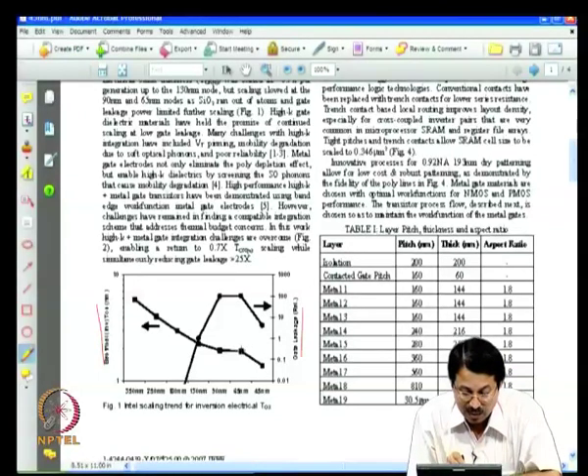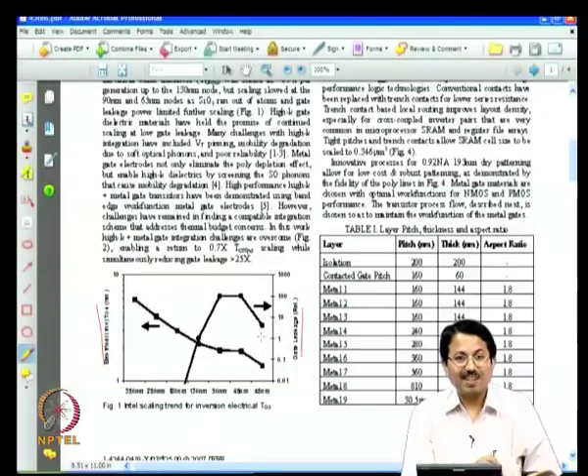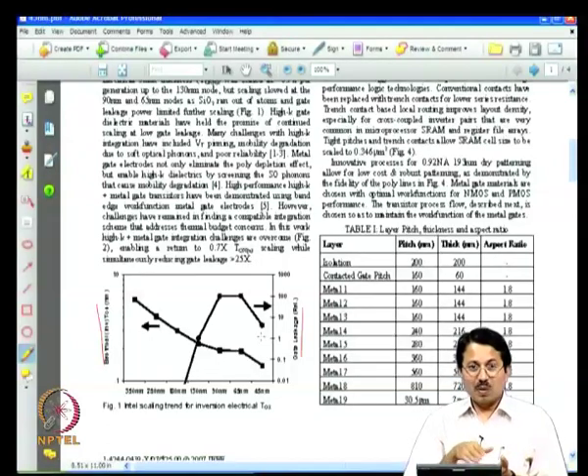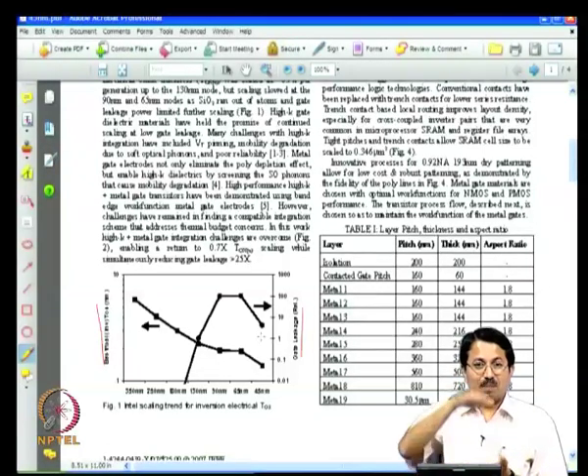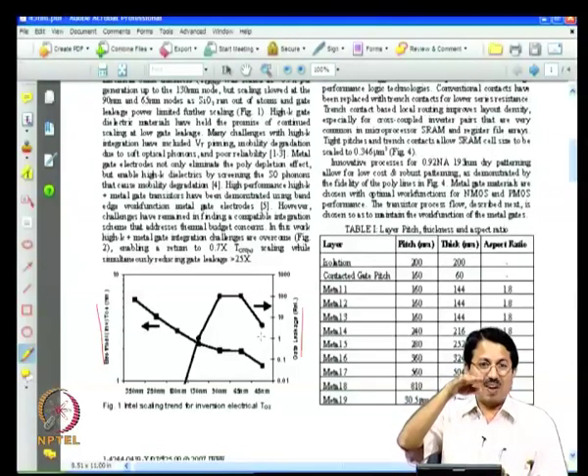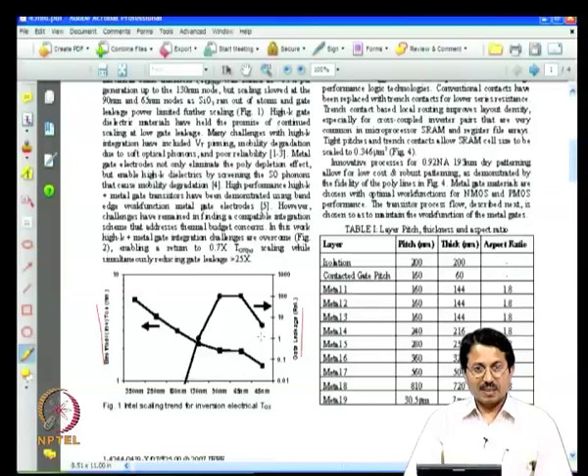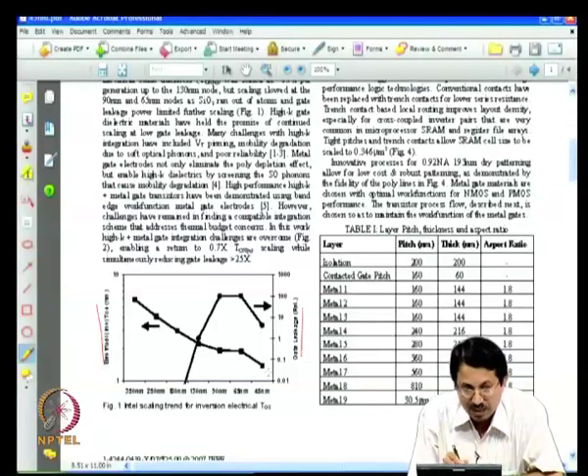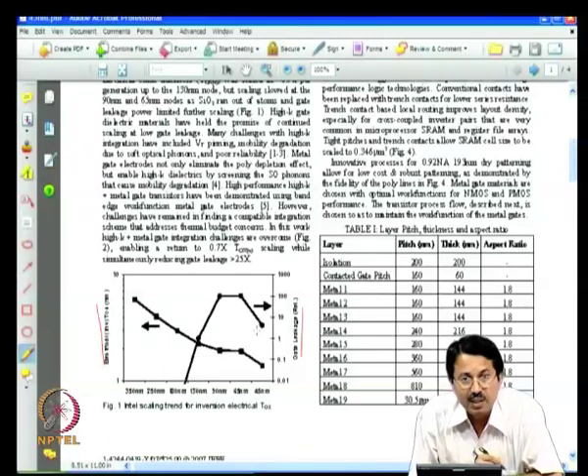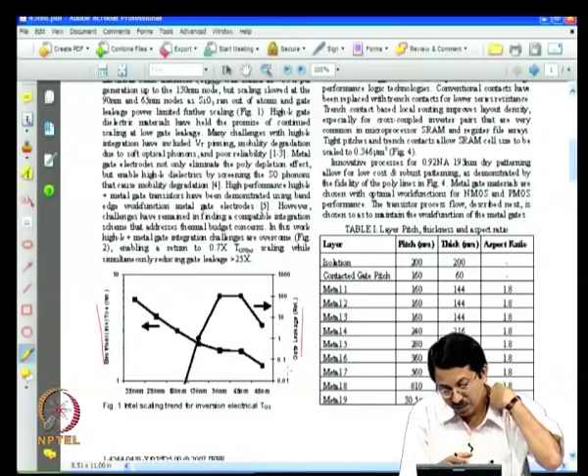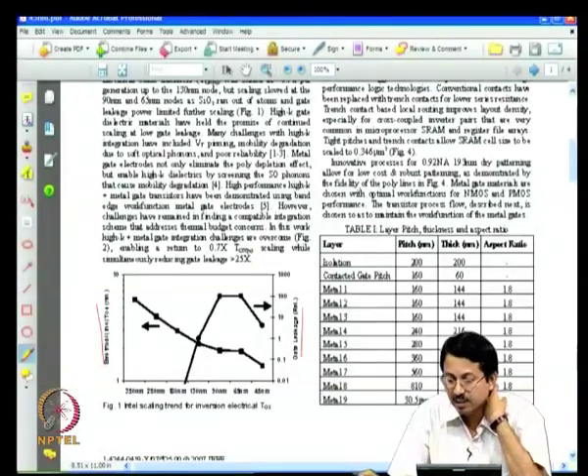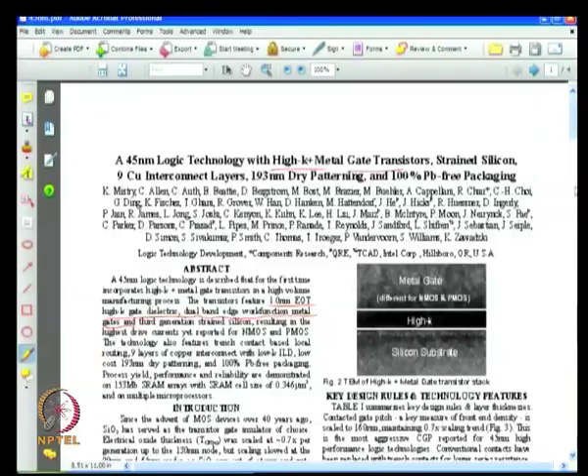Now with the high K technology the EOT came down, but the leakage did not increase, the leakage also came down. Because it is an EOT of 1 nanometer but indeed a thicker physical oxide, direct tunneling is suppressed, and hence you got the best of both worlds. You got lower EOT and lower leakage current, that is why you want to use high K gate dielectric. That is illustrated very nicely here, showing the trends in different technologies. So this is a high K, and the metal gate is different for NMOS and PMOS.